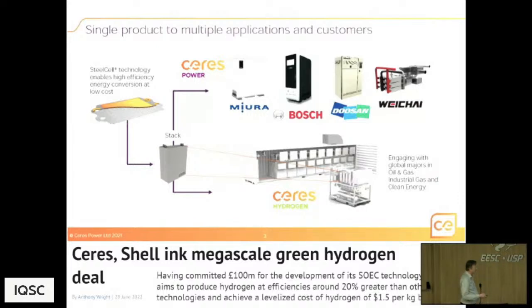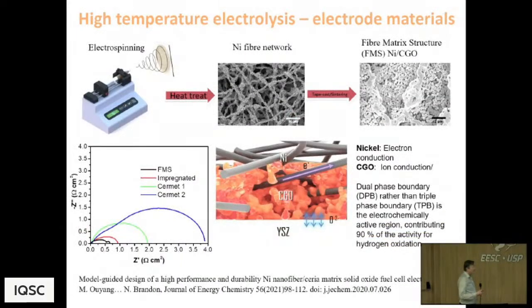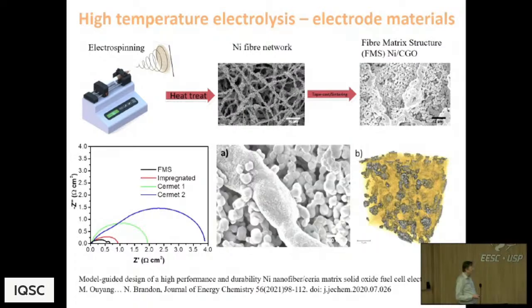And in terms of what we do in my group, in our research, we remain very interested in some of the fundamentals and how you continue to evolve the materials. So we're doing things like electrospinning to produce interesting fiber structures, which we think are much more robust, particularly focusing on electrolysis mode, where you can have problems with nickel migration at the high steam concentration. So we're interested in developing novel fibrous structures for these applications, which we continue to work on today.